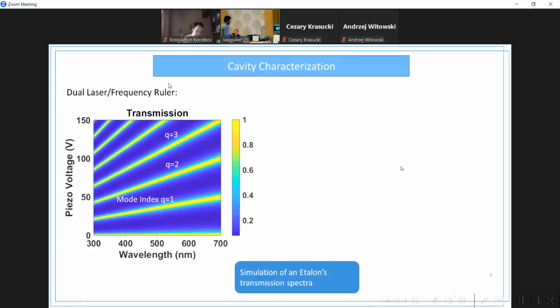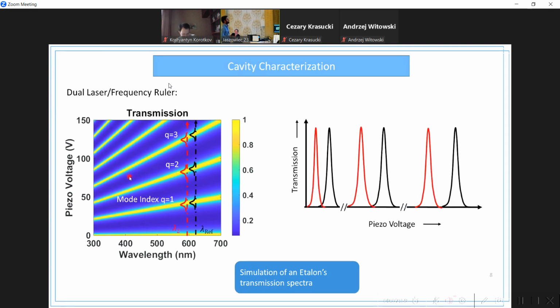So if you imagine a transmission spectra of an etalon, if you change the cavity length - since in our case we are tuning the cavity length by tuning the piezo voltage, so this axis is piezo voltage - you scan the wavelength in a number of steps, and you would observe these straight lines which are the cavity modes. Now, if you shine two lasers, what you are going to get is 6 peaks corresponding to these modes, 2 peaks corresponding to each mode because you are using 2 wavelengths.